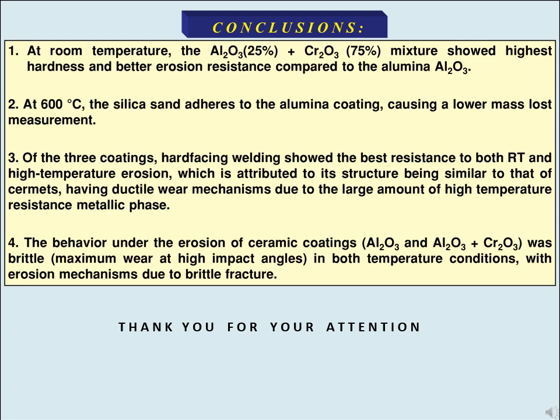Conclusions. 1. At room temperature, the mixture of alumina 25% and chromium oxide 75% showed highest hardness and better erosion resistance when compared to the alumina alone. 2. At 600 Celsius degrees, the silica sand adheres to the alumina coating, causing a lower mass loss measurement. 3. Of the three coatings, hard-facing welding showed the best resistance for both room temperature and high-temperature erosion, which is attributed to its structure being similar to that of cermets, having a ductile wear mechanism due to the large amount of high-temperature resistant metallic phase.